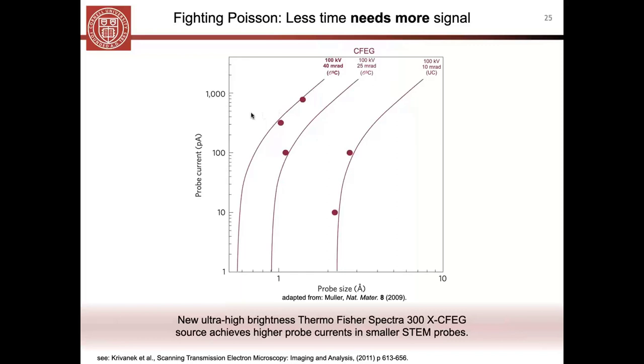So what you can do is, in a STEM, particularly for high resolution STEM, the probe current that you're using, so the amount of electrons that you're putting through your sample at any given time, is tied to the probe size. And this is limited by several things, but in part by the source brightness of the electron source that you're using, whether it's a Schottky or an X-FEG or whatever it is, cold FEG, things like that. So just to walk through this plot, you can see now as a function of probe size, so we want to be down on this end with small probes, you can track out the probe current of your STEM. And of course, we want to be up on this end. We want to have more current in a small probe to get more signal, but preserve our spatial resolution.